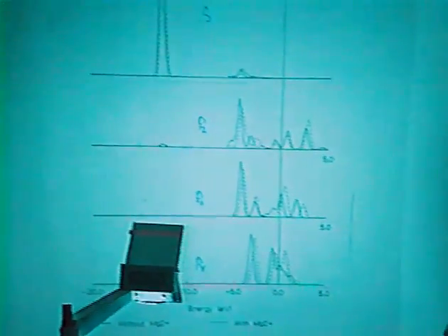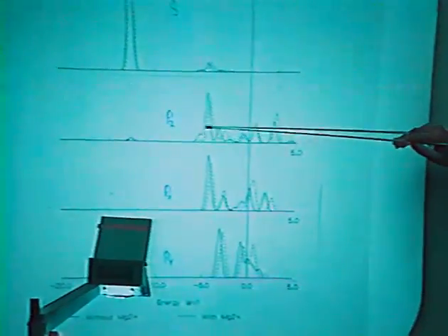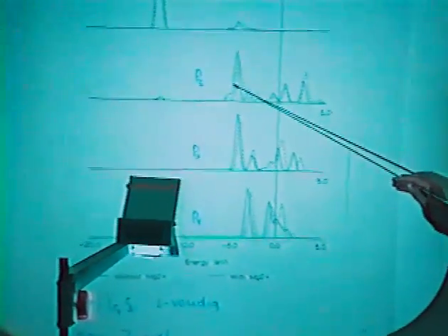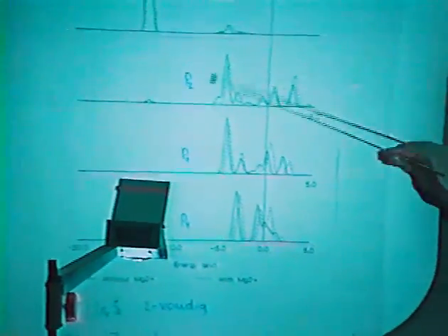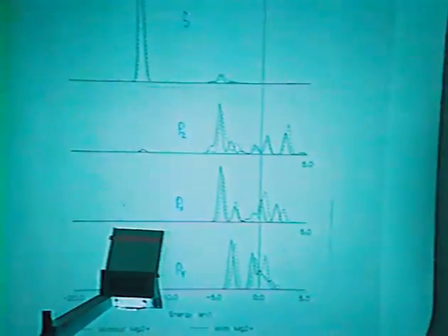And let's just concentrate on the solid lines, because the dashed lines are in the presence of the cation. I won't look at that right now. With the solid lines, PZ, you see it splits off quite heavily, because this is the isolated sulfur peak, and this is what is split off. So PZ contributes, and also PX and PY contribute. And this is also an explanation of why two-fold and three-fold bonding is favored more than one-fold bonding, because PX and PY are very important. They have more interaction with two or three atoms than with just one. Okay. Well, that's about the density of states.